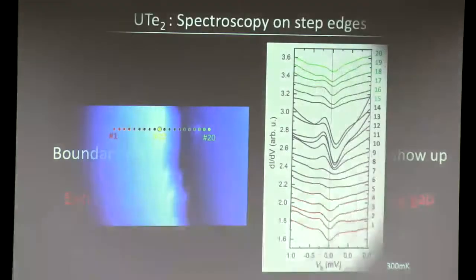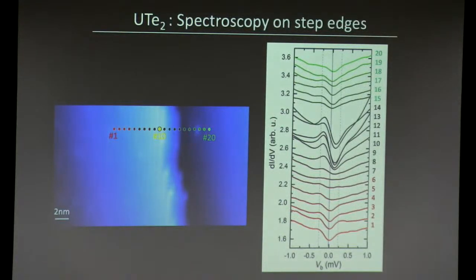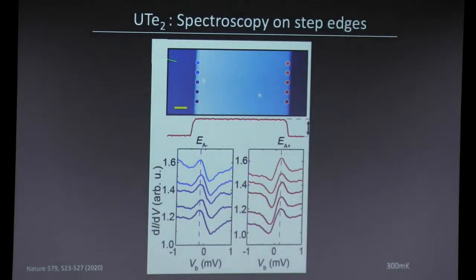Let me show you data along a step edge. This is a line cut. Far from the step edge, this is spectrum 1, where you see the superconducting gap. As you go closer to the step edge, extra density of states emerges inside the superconducting gap, but only on one side of the Fermi energy. If you look at two step edges in opposite directions, this extra density of states appears on opposite sides of the Fermi energy along each.